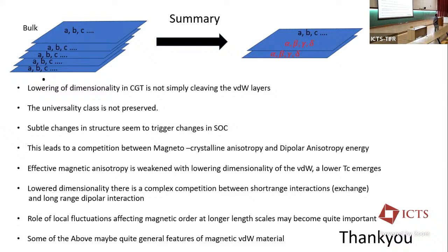As you're thinning down the sample, the transition temperature should also decrease, right? We find that in this case, as I showed you, it's close to 67 Kelvin, it's 65 or so. But there is another transition which is at lower temperature. Now, if you take the average of these two transitions, then certain experiments do an average measurement which can show a lower transition. But there are two distinct transitions inside the system.